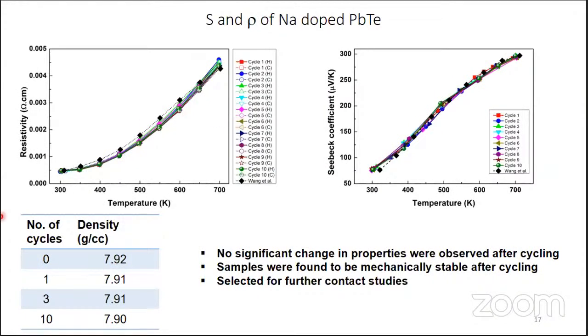We have done several cycles and consistently it gives the same density. There is no variation in density. The resistivity and Seebeck coefficient are very consistent. There is no porosity after measurement. So relatively, this material is much better than this one. So we use this material for making the thermoelectric module.